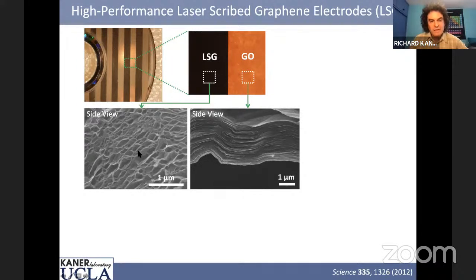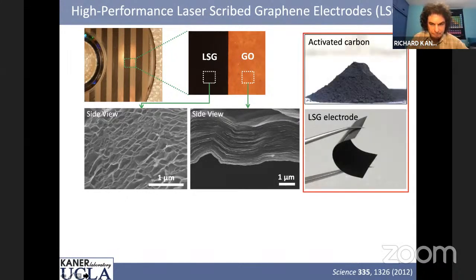And the other thing is that graphene is pure carbon. Well, even if we do this experiment in air, we've gotten to above 99% carbon. So basically, by burning off CO2, it leaves behind this porous network. If you add an electrolyte, it will fill in these pores and you can access every surface, or just about every surface. And so this is why this works so well for electrochemical devices.